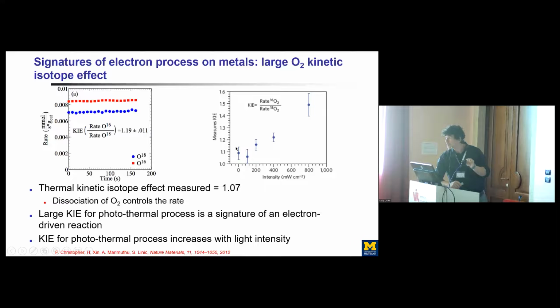On the other hand, if you have these electron-driven processes where electrons are scattering through these anti-bonding orbitals, you would expect the kinetic isotope effect to be larger under the same conditions. So we do that measurement, again the same experiment, oxygen 16, oxygen 18 switch, but now with light, and we see the kinetic isotope effect goes up to about 1.1 or 1.2 at low light intensity, for example, sunlight intensity. And as we increase the light intensity, that kinetic isotope effect goes up further. So this difference in the kinetic isotope effect and this positive relationship between the light intensity and the kinetic isotope effect is a signature of an electron-driven or hot charge-driven chemical process on a metal surface, as discovered by Ertl and others in the 1980s and 1990s, working with single crystal surfaces.